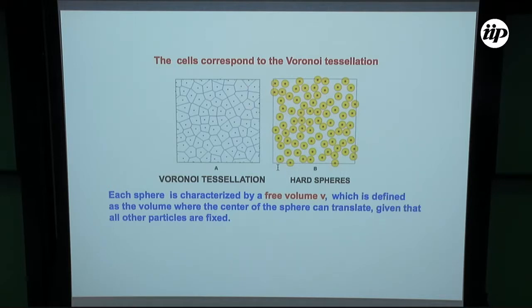So each sphere now is characterized by a free volume v. This free volume is defined as the volume where the center of the sphere can translate, given that all the other particles are fixed. So you can imagine when the free volume is 0, that particle is a jammed particle, essentially. So when the free volume would be 0, on average, that would correspond to a jamming transition.